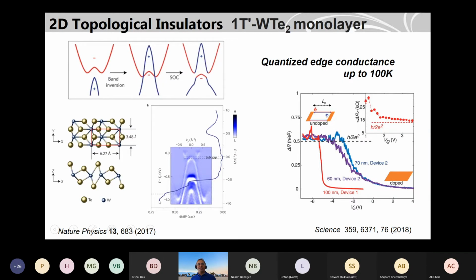And also with the STM experiment, they see this gap. And more importantly, in the transport experiment with Hall bar type of devices, what people measured in 2018 was this quantized edge conductance up to 100 Kelvin, because the gap you open is much larger, so you can measure also up to high temperature.